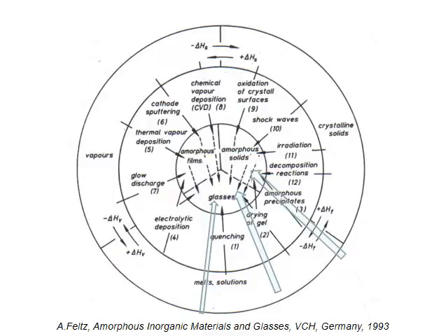Processes of precipitation from solutions often lead to amorphous precipitates, as in the case of red amorphous selenium, sulfides of arsenic, antimony, germanium, tin, and numerous other metals or metal hydroxides. Electrolytic separation using a high current density leads to amorphous layers, such as amorphous germanium. The first examples of metallic glasses were obtained by this means.